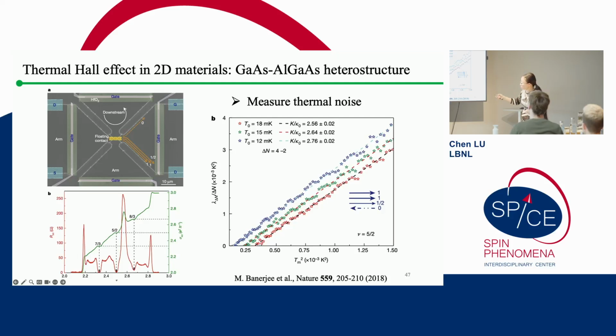For 2D material studies of the thermal Hall effect, you need a very heavy nanofabrication process to first build a device. And then you measure the thermal Hall effect coming from the thermal noise of the material instead of measuring the temperature directly. So if we have 2D people here who are interested in studying the thermal Hall effect in 2D materials, you can go into this reference and all the other related references for the experimental setup.